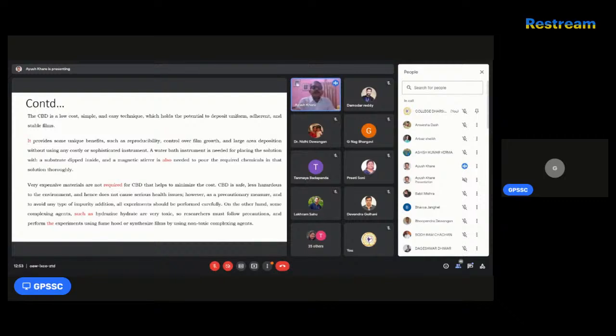But we have to take precautions to avoid any impurity addition. Since vacuum is not there, manual treatment is done, so maybe certain defects or impurities are added while preparing samples, so we have to check, right? On the other hand, some complexing agents such as hydrazine hydrate are very toxic, so researchers must follow precautions and perform the experiment in a fume hood. A fume hood is a cavity sort of thing where everything is done inside a box, right? So that is a fume hood to deposit such films.